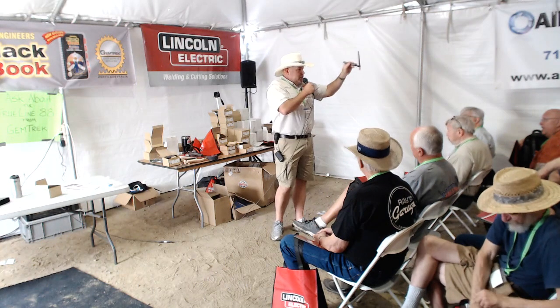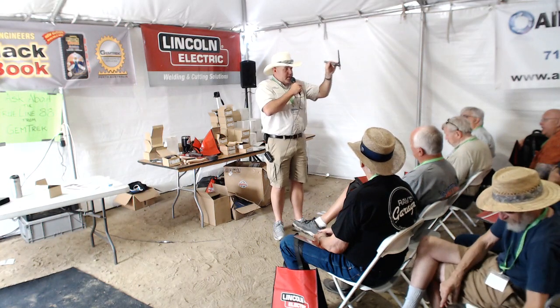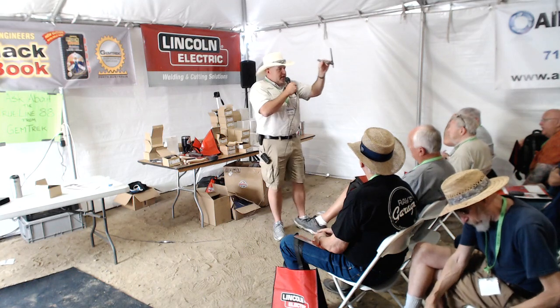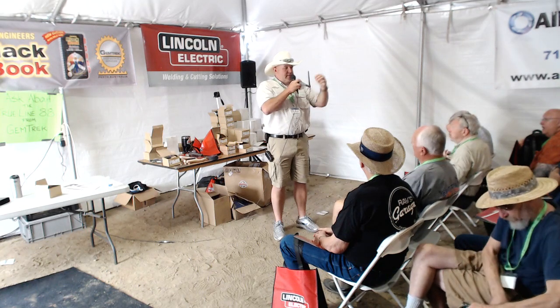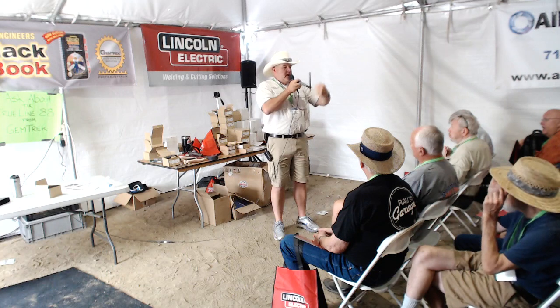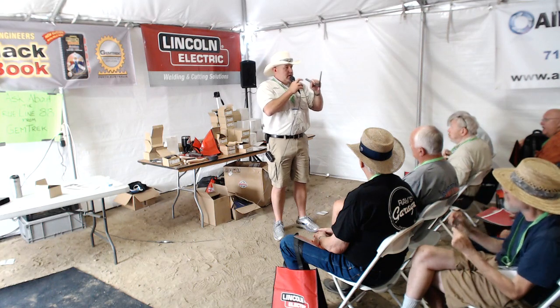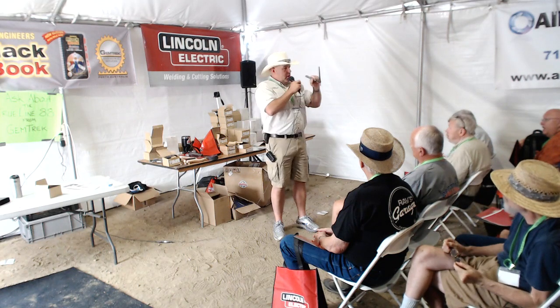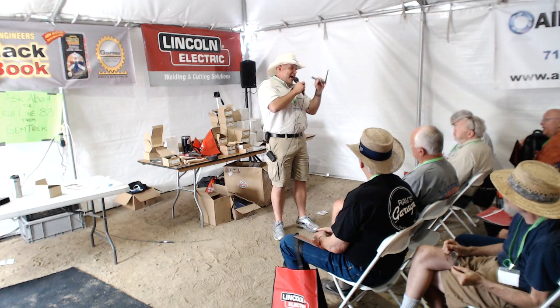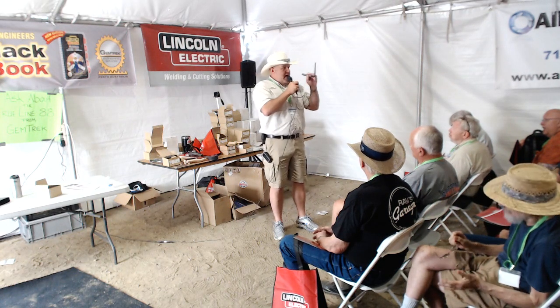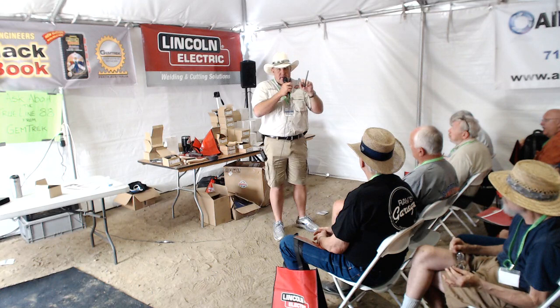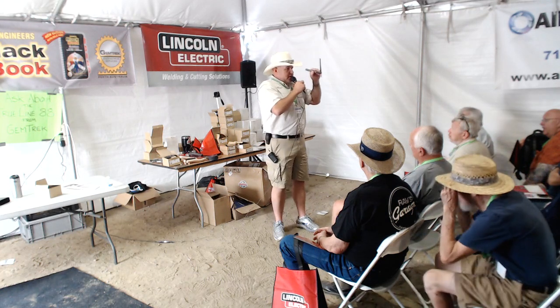Torch angle is extremely important. Okay, let's talk about that for 1 second. 90 degrees to the plate. So you see that if the plate was laying here like this, 90 degrees, right, in our direction of travel. We're allowed a 15 to 20 degree back angle in direction of travel. Every beginner does this. Guys, listen to me, because you're going to catch yourself.